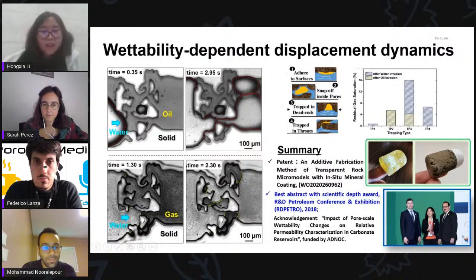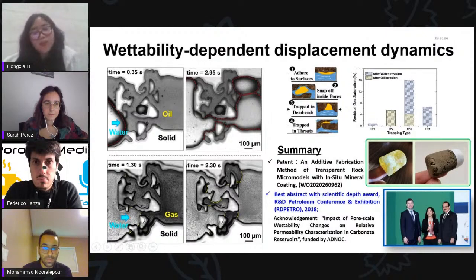With all these studies, we summarized the different trapping mechanisms, where the oil is preferably trapped on the surface, in dead-end pores, or in narrow throats, and the percentage depends on the wettability, of course. So this type of 3D printing combined with mineral coating can fabricate rock microfluidic chips, and we can even scale up to fabricate the whole core.